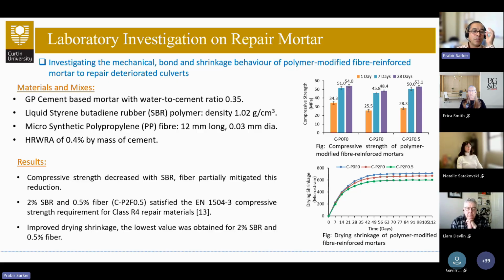Some of the mortars trialed in the lab were cement based mortar with a water to binder ratio, water to cement ratio of 0.35, and a liquid styrene butadiene rubber SBR polymer was added to it, along with a microsynthetic polypropylene fiber. A high range water reducer was also used.